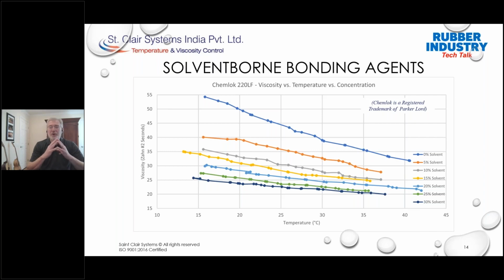Now, if we project the recommended spray viscosity range of 22 to 28 seconds across these curves, we can see the importance of the interaction between dilution and temperature in the actual viscosity of the fluid. It's apparent that depending on the temperature, dilutions as low as 5% can actually be used, whereas dilutions of 25 to 30%, which is on the low end of the recommended range, can produce viscosities that are actually outside of the recommended range. It also seems pretty clear that dilutions greater than 30% will produce viscosities that are below that recommended 22-second minimum for spraying across nearly all temperature conditions. So this is a really important finer point about the compound and its usage.